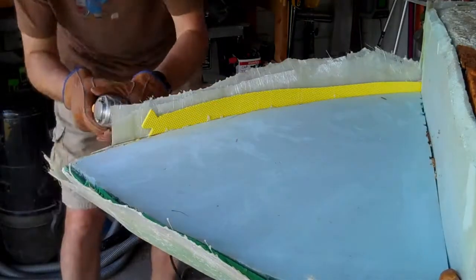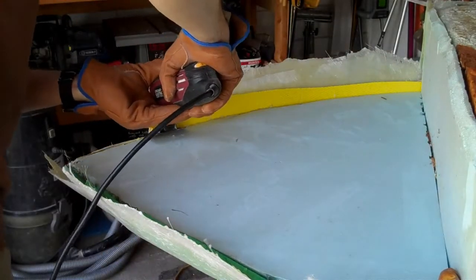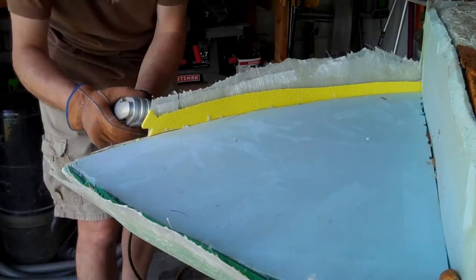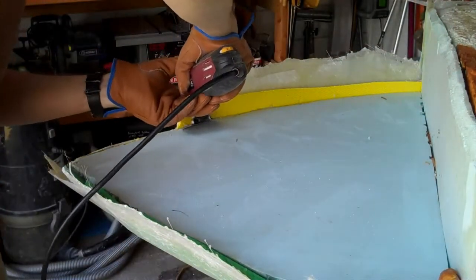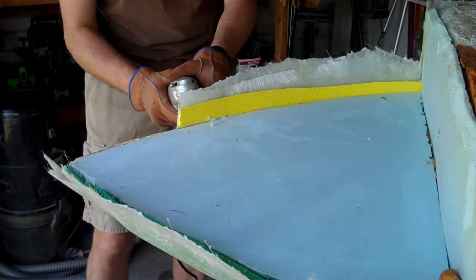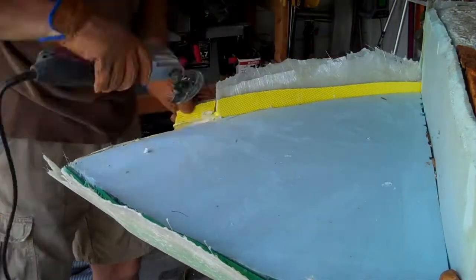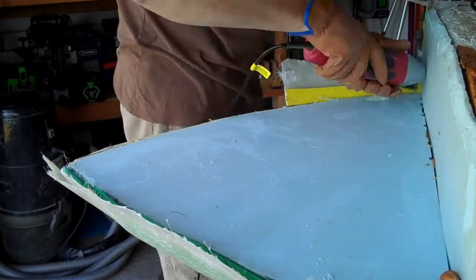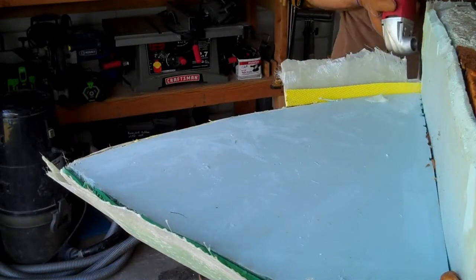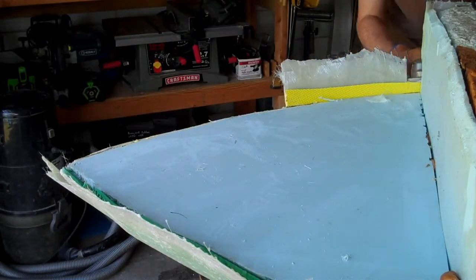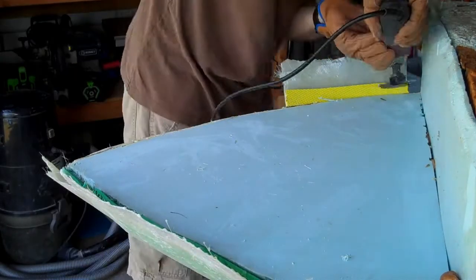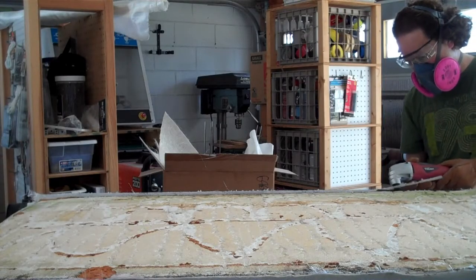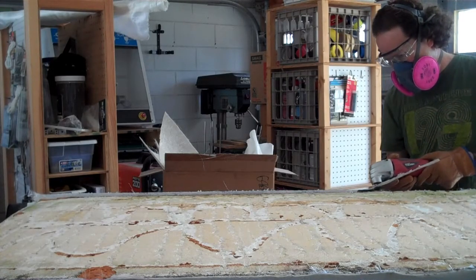I find that an oscillating cutoff tool is perfect for this job. I used a drywall disc for most of the work, combined with a 1-inch square plunge cutter for detail work near the edges. Expect your blades to dull faster when cutting fiberglass than wood. Notice that I'm cutting at a slight downward angle from the foam that will shape the top surface. While I had the oscillating cutter out, I also cut away the smaller overlaps from the edges of the pontoon itself.